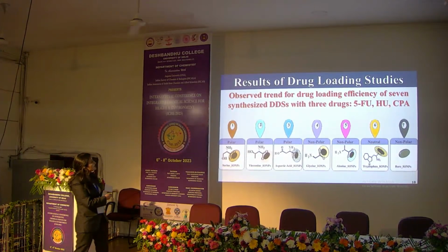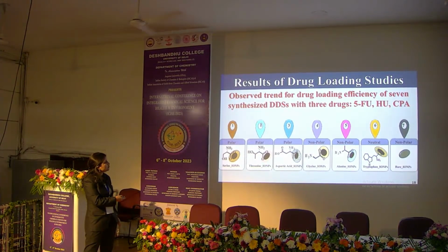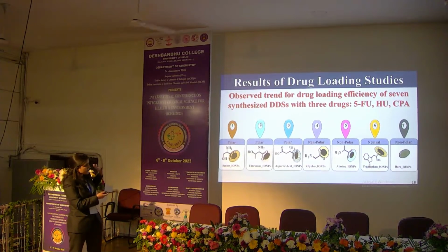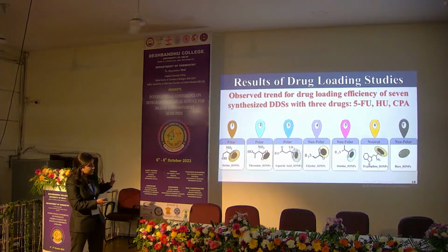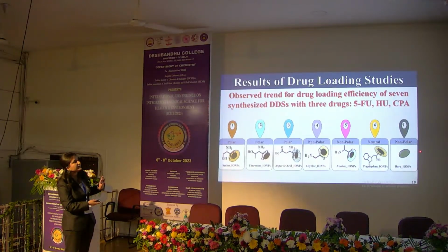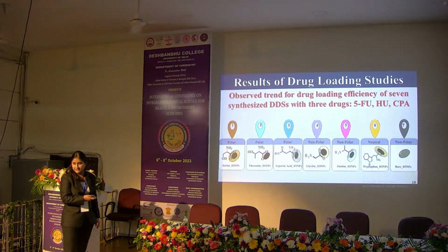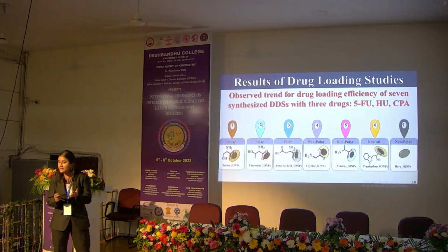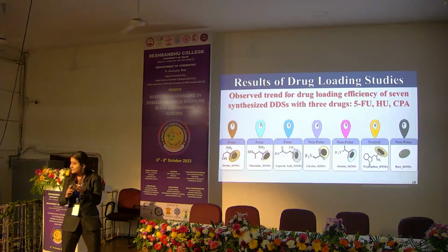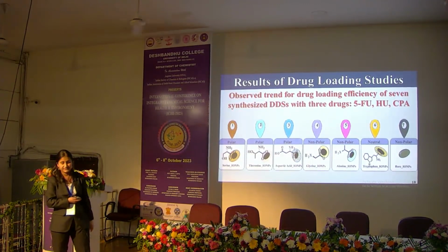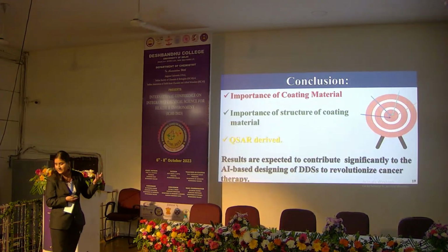We can see the polar group of amino acids were shown to have higher drug loading efficiency in comparison to the non-polar group of amino acids. Although, the non-polar group of amino acids were also shown to have higher drug loading efficiency in comparison to bare. So this suggests that the coating not only increases their colloidal stability and their interaction with the biological molecules, but also their drug loading efficiency. So we can conclude.